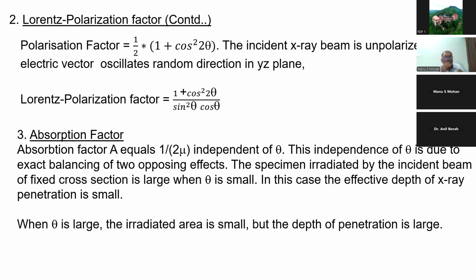So you have the Lorentz polarization factor. Taking all this into account, there is the Lorentz factor and a polarization factor separately. The polarization factor arises because the incident X-ray beam is unpolarized, since X-ray is an electromagnetic wave - the electric field oscillates perpendicular to the path direction, so it is unpolarized. This also affects the intensity.